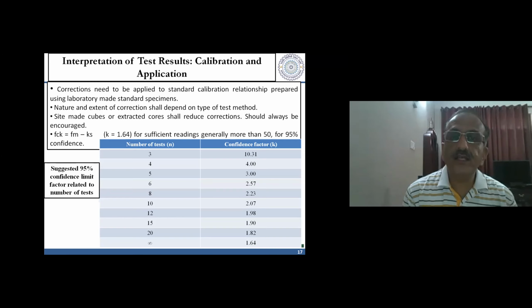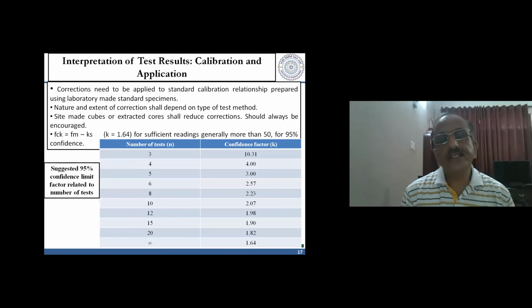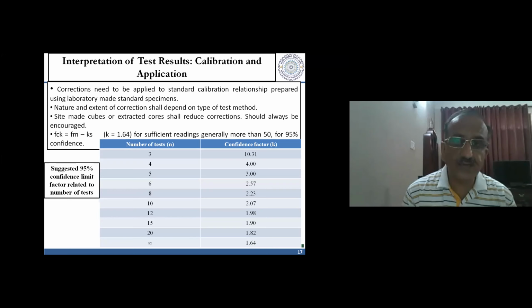But if it is an old structure and it is secondary testing, cubes are not available. There the cores are to be extracted. So generally the guidance available in the codes, and also based on our experience, for each grade of concrete you should take 9 cores. That means 3 locations should be chosen, and 1 location will give you 3 cores, the average of that being one observation. So 3 observations should be taken for each grade. So 9 cores, and for each observation, each location, you should take the corresponding in-situ test value also.